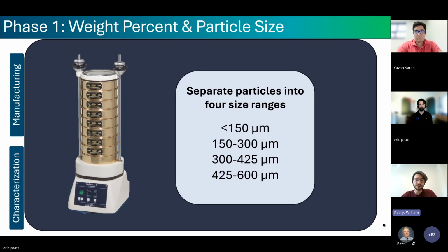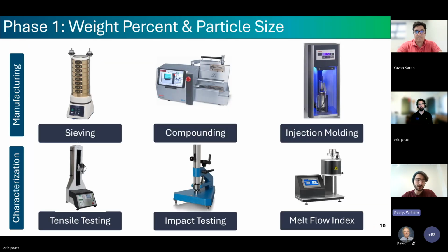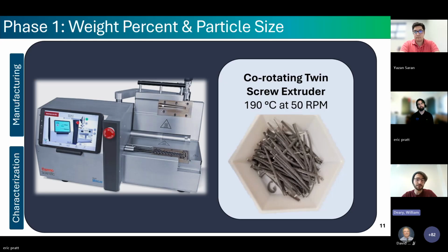After isolating our particle size fractions, the next step was compounding those fractions with polypropylene. So our compounding was performed using a Thermo Scientific Minilab 3 microcompounder, which we operated at 190 degrees Celsius and 50 RPM with batch sizes of approximately 5 grams of material.